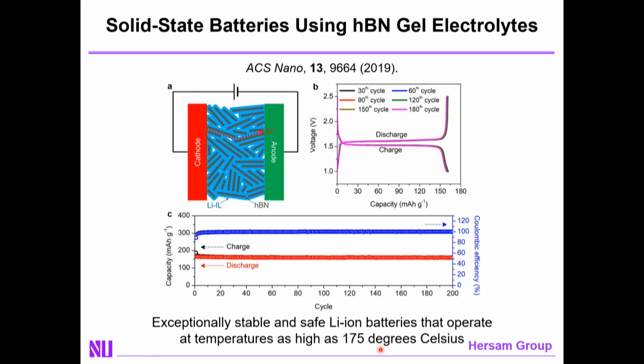If you were to take a conventional lithium-ion battery and put it on a hot plate at about 60 degrees C, it would go up in flames due to the flammable solvents that are used for the liquid electrolyte. These batteries are perfectly rock-solid stable to at least 175 degrees. In fact, at this temperature, what's degrading is not the electrolyte, but the electrodes themselves.